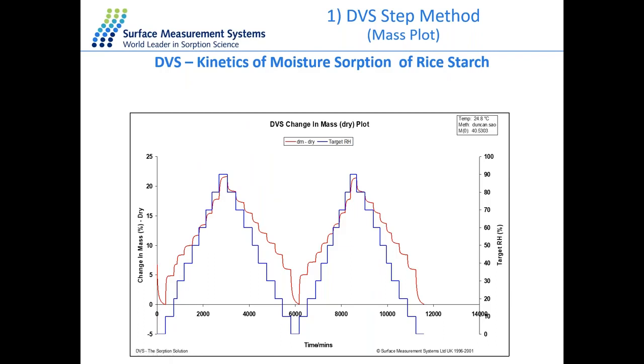Like I showed before, we can have a 2-cycle step method for our DVS experiments. In this example, we're looking at the kinetics and moisture absorption of rice starch. We have our experimental target relative humidity in different steps up until about 90% relative humidity, with absorption and desorption, and a second cycle, again absorption and desorption. Our red line is the mass uptake of our rice starch material. What's interesting is that we're getting the same experimental data for cycle 1 and cycle 2.